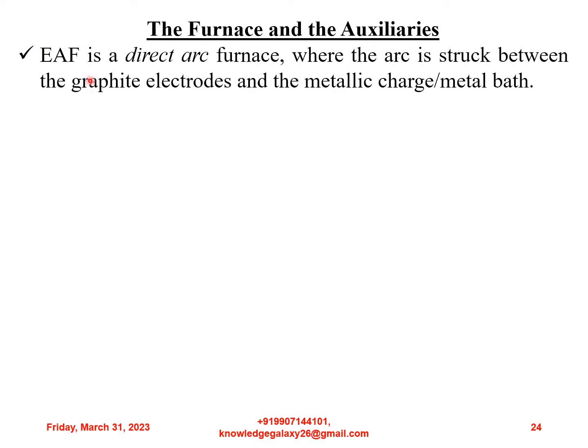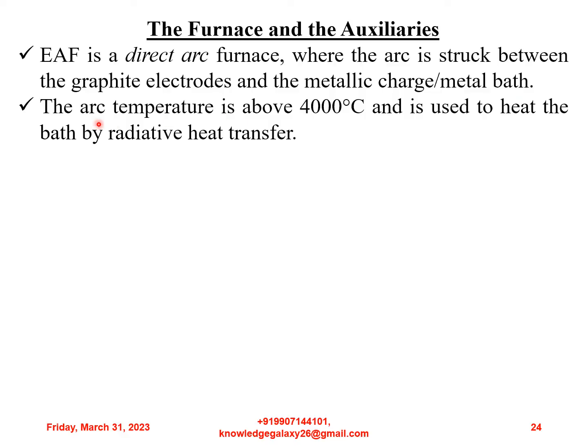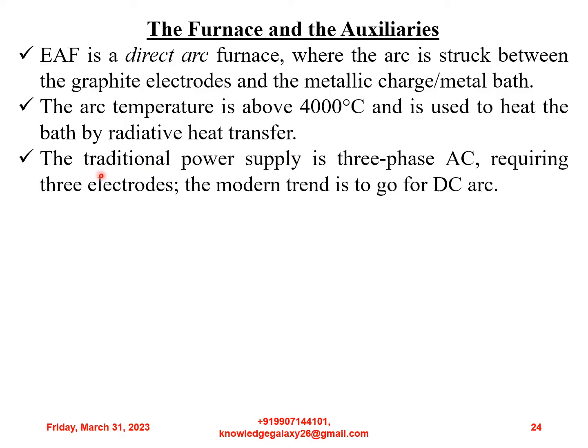So now let us discuss the furnace and its auxiliaries. Electric arc furnace is a direct arc furnace where the arc is struck between the graphite electrodes and the metallic charge or metal bath. The arc temperature is above 4000 degrees Celsius and is used to heat the bath by radiative heat transfer. The traditional power supply is three-phase AC requiring three electrodes. The modern trend is to go for DC arc.